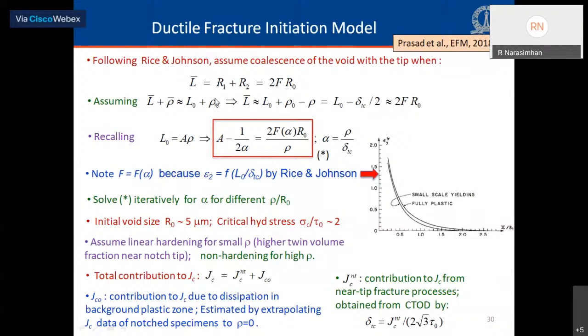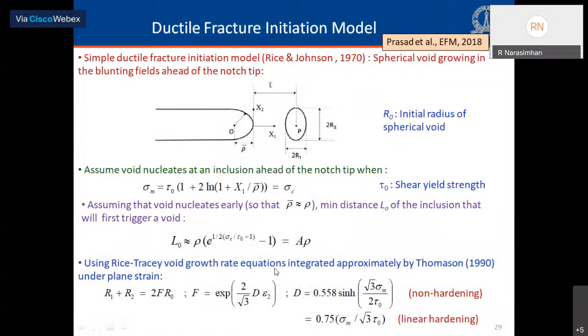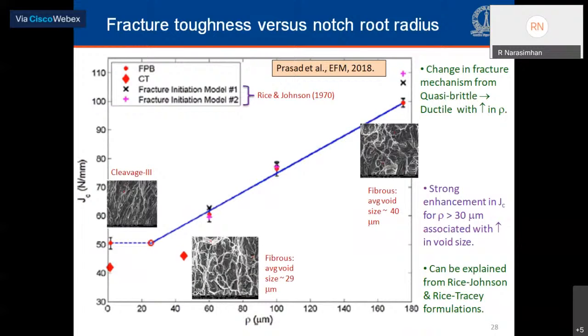The Rice-Johnson assumption is that coalescence of the void with the crack tip takes place when the distance between them becomes equal to the sum of the principal radii. We applied that criterion and came up with the equation in the box, a nonlinear algebraic equation for the parameter alpha, which is rho divided by delta Tc, the notch root radius divided by the critical crack tip opening displacement. Now we solve this equation numerically using the Rice-Johnson slip-line solution for the plastic strain field ahead of the tip, and determine the delta Tc, the crack tip opening displacement corresponding to different notch root radii, related it to the near tip Jc by the expression at the bottom of the slide, combined it with the dissipation contribution JC0, which we approximately inferred, and plotted it against rho, and that's what you see here by the plus symbols. So the model seems to work pretty well in predicting the trend.